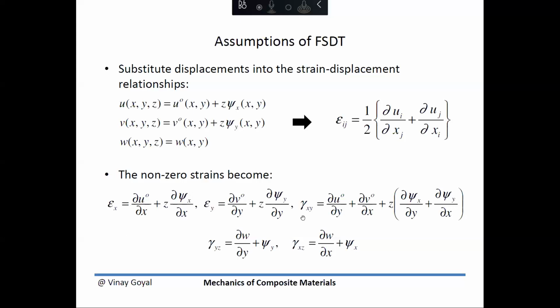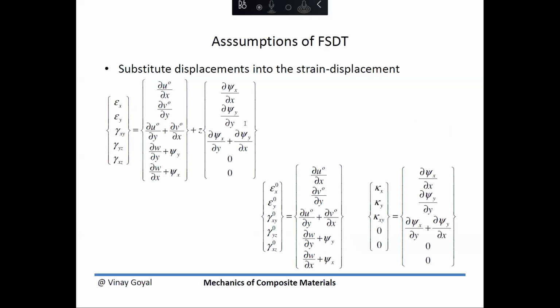Notice how I don't have epsilon ZZ. Epsilon ZZ is 0 because we have assumed that the transverse deflection does not depend on Z. In other words, the derivative of W with respect to Z is 0. With these 5 non-zero strains, the unknowns of these theories becomes 5. 1, 2, 3, 4, 5, which means I need 5 equations to be able to solve for these 5 deflections, or these 5 kinematic quantities.